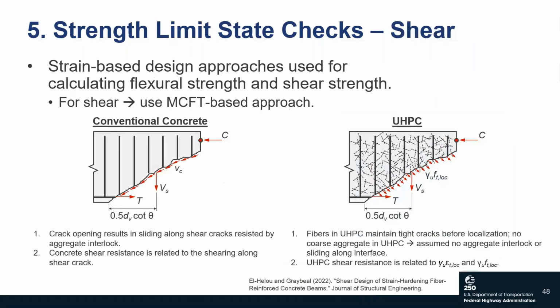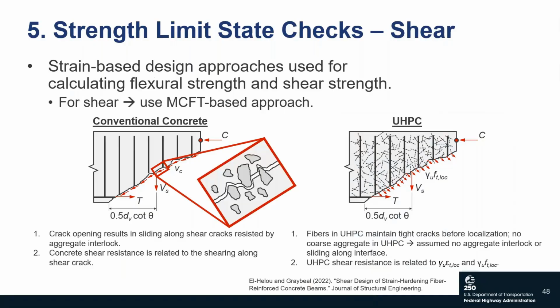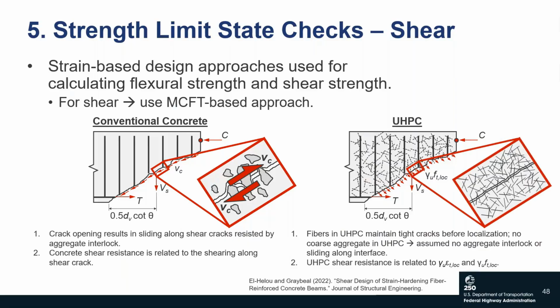In terms of shear, we're going to, again, use a strain-based design approach, and we'll use a modified compression field theory-based approach, just like conventional concrete. One of the main differences is the resistance mechanism. With conventional concrete, you have your shear crack, you have sliding along that shear crack, and that interface shear is what's going to resist your shear. With UHPC, the fibers keep your crack tight, and UHPC itself has a high tensile strength. So that's going to be our primary resistance mechanism.